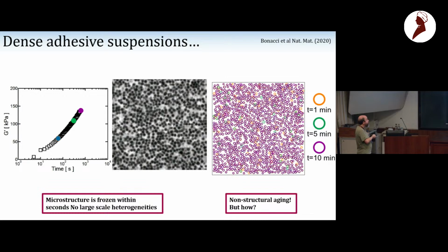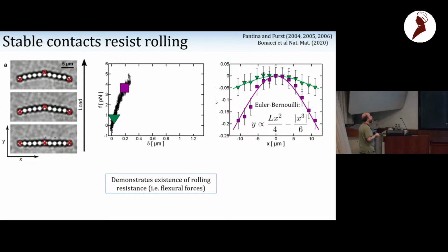Now, we see aging on the modulus, and the only thing that can age are the contacts. There is a beautiful experiment that was done first by Pantina and Furst, who created the technique where they take colloidal particles, and using optical tweezers, they manipulate the particles and form a rod of particles. The first thing which is amazing is that you have colloidal particles that stick together. They do a 3-point bending test: you hold the end particles, you grab the central particle, you pull on your rod, and you see something that is bending like a rod.